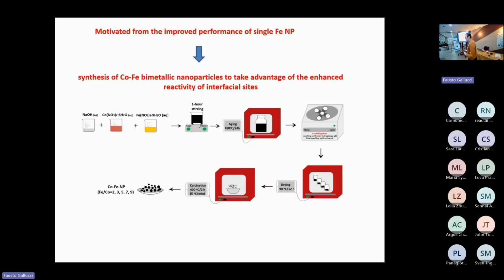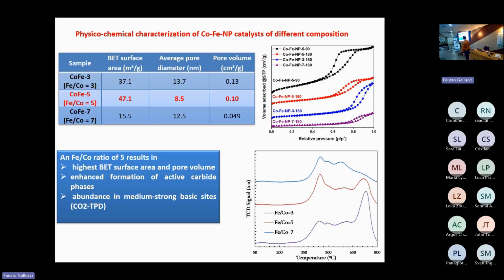Motivated by these results, by simply fine-tuning the iron nanoparticles, we proceed to the synthesis of bimetallic nanoparticles, cobalt iron nanoparticles of different composition. Extended physicochemical characterization of cobalt iron nanoparticles of different composition reveals that there is an optimum iron cobalt ratio of about 5, which results in the optimum textural properties, enhanced formation of active carbide phases, and also an abundance of medium to strong basic sites.